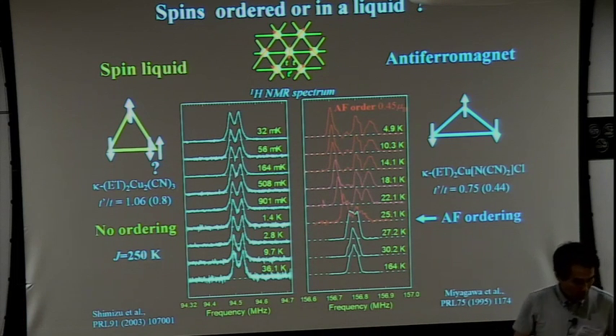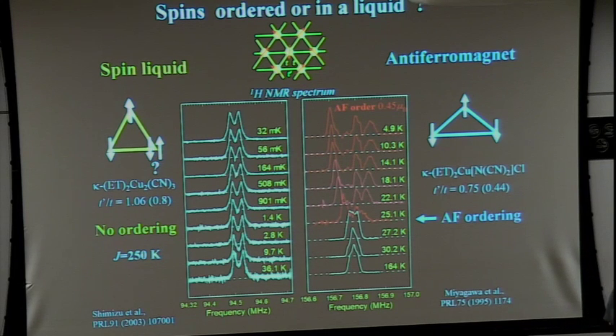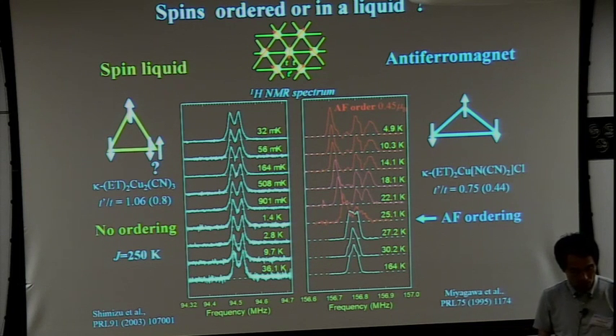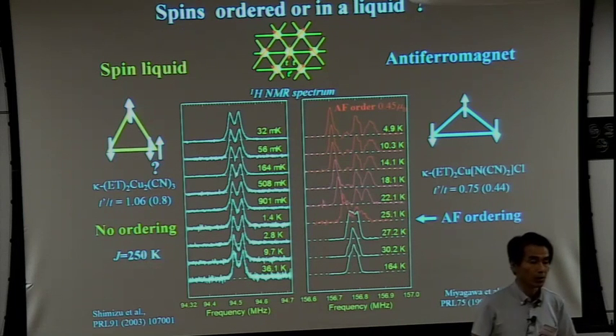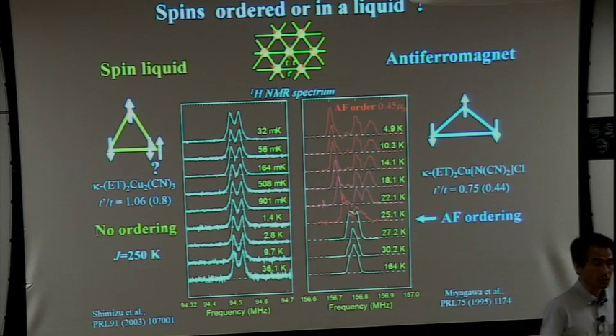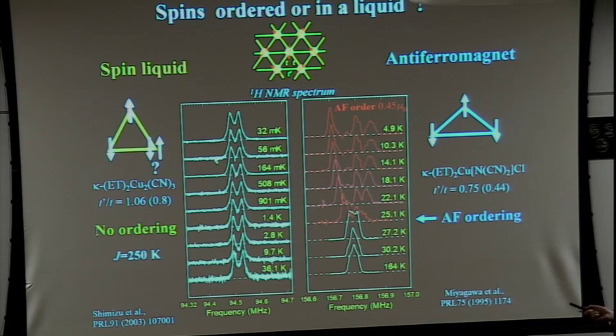Okay, let's resume the issue of the spin liquid. In yesterday's lectures, I showed you some experiments which give evidence of the quantum spin liquid nature and magnetic ordering, depending on the degree of frustration of the lattice. I showed two materials: one is the deformable triangular lattice, and the other is the nearly isotropic triangular lattice. The deformable triangular lattice shows clear magnetic ordering below 25 or 26 kelvins, which is clearly indicated by the splitting of the NMR line, as I showed you yesterday.